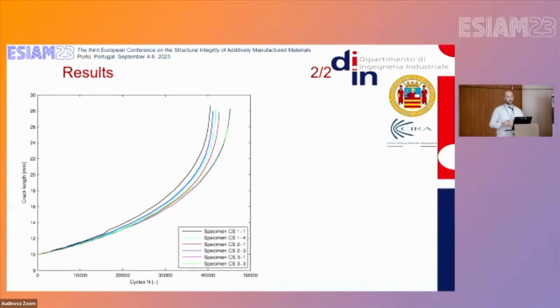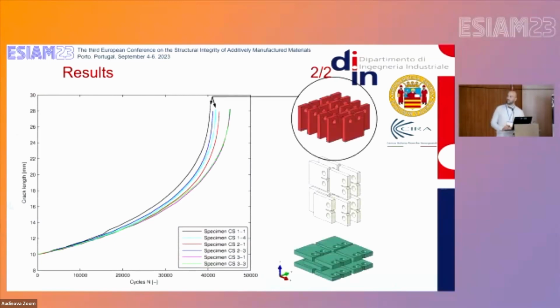to a comparison among multiple specimens, we concluded with this chart. Here we can see the specifics of this curve. We can see that the green specimens were those that provided a slightly better fatigue life, so longer, even though it has to be admitted that I was personally expecting slightly larger deviations between the curves.